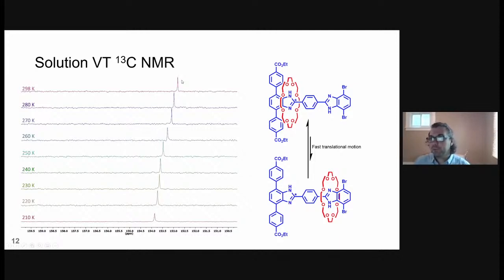So when we do these dynamic NMR experiments, what we're looking to see is at high temperature, a single peak corresponding to the chemically averaged environment as the ring moves very rapidly between these two different positions. As we cool it down, this peak, in theory, will broaden out, and then the motion will slow sufficiently that we see both of these forms on the NMR time scale, as the motion is slower than the speed at which the NMR operates. And when we see both the single peak at high temperature and the two peaks at low temperature, we can then start to simulate the NMR spectra and extract things such as the energy barrier for translation, and we can work out the rate at which it moves at each of these temperatures.